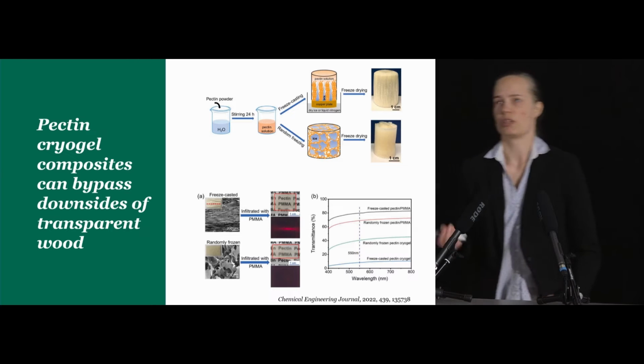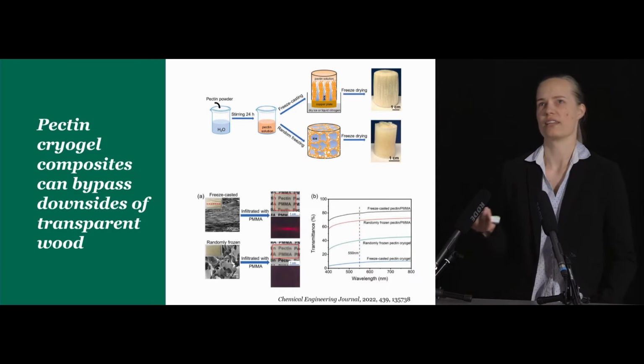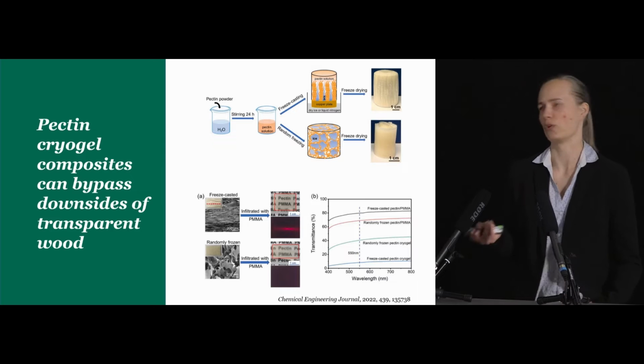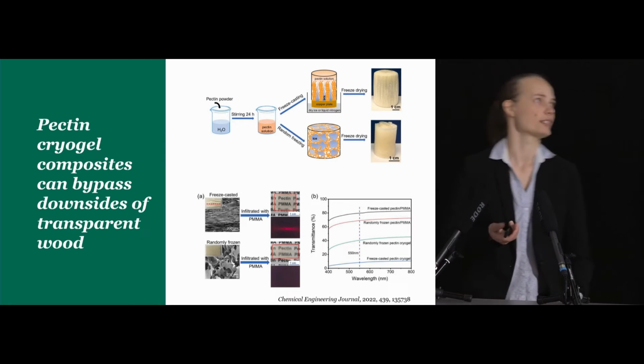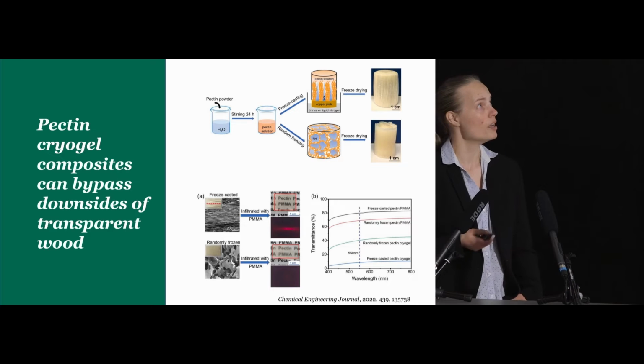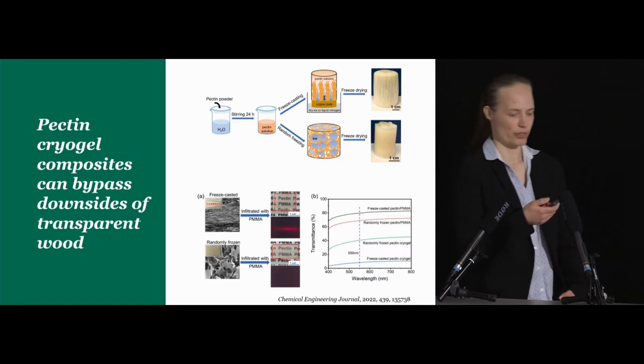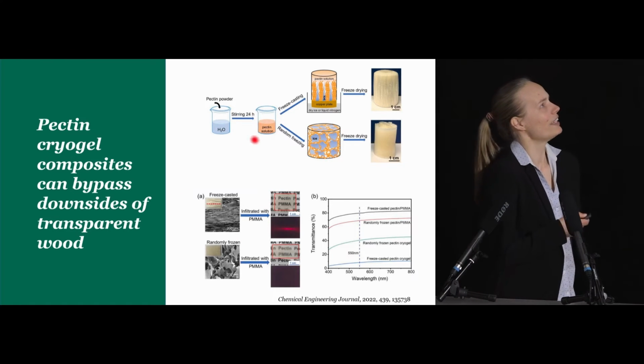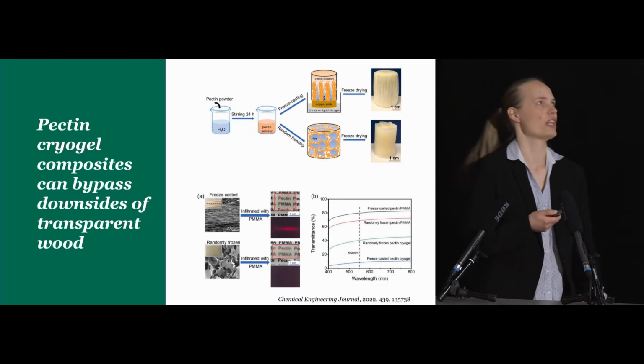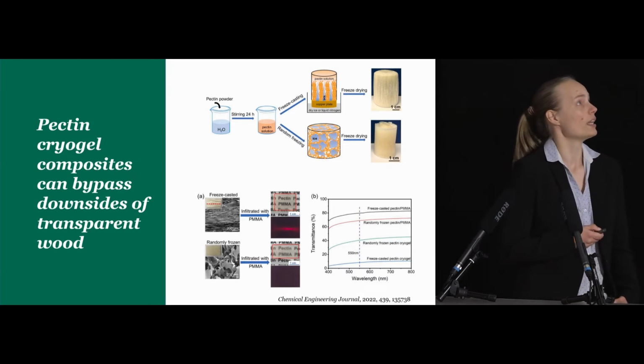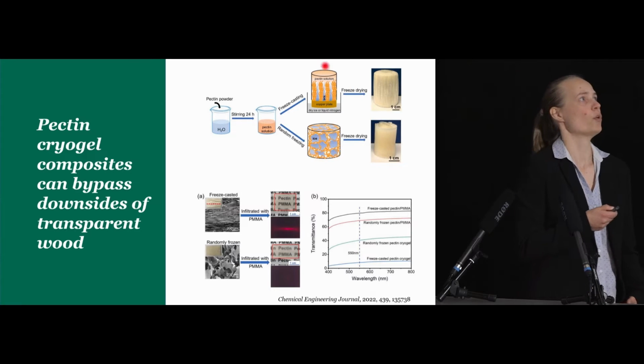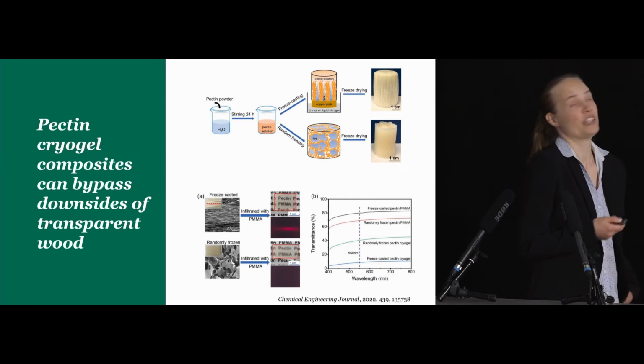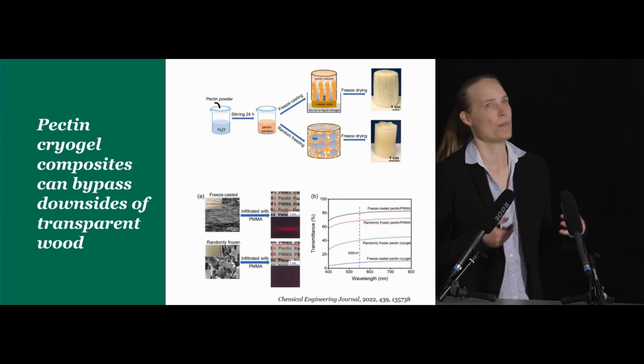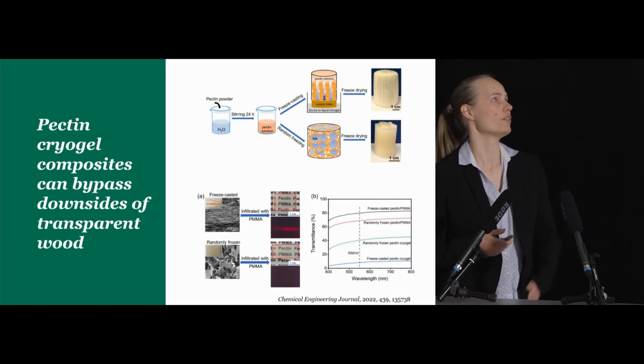Pectin is great because you can also source it from bio-waste. For instance, a lot of fruit peel waste contains pectin that can then be extracted. So what we did here was that we started from pectin solution, and then by changing the freezing strategies, we could get either random morphologies or highly aligned anisotropic morphologies. You can imagine this resembles a little bit the structure of a delignified wood.